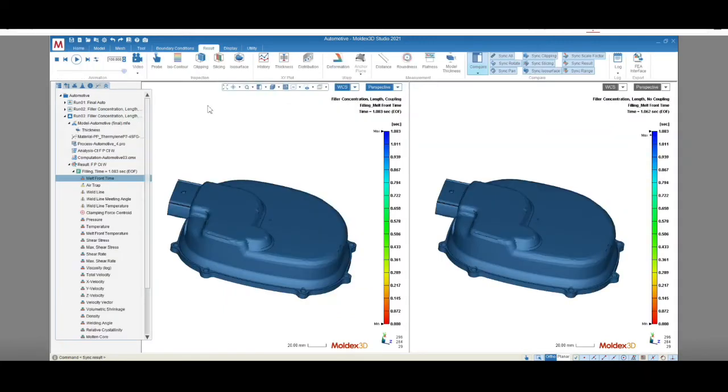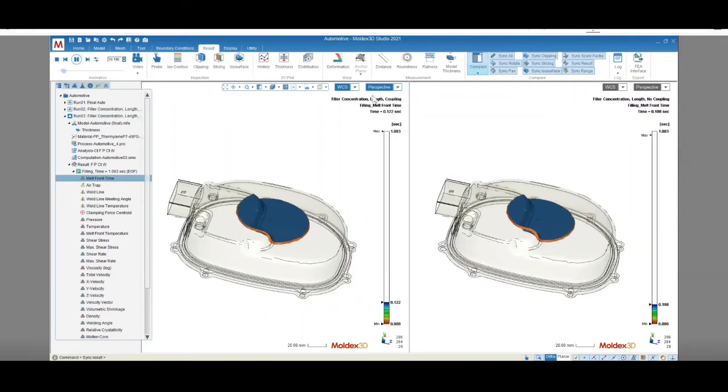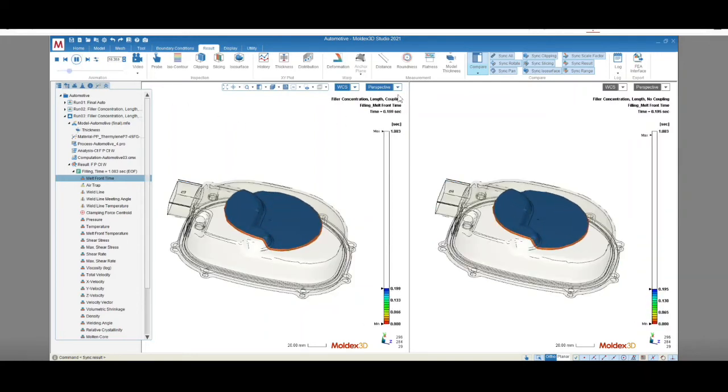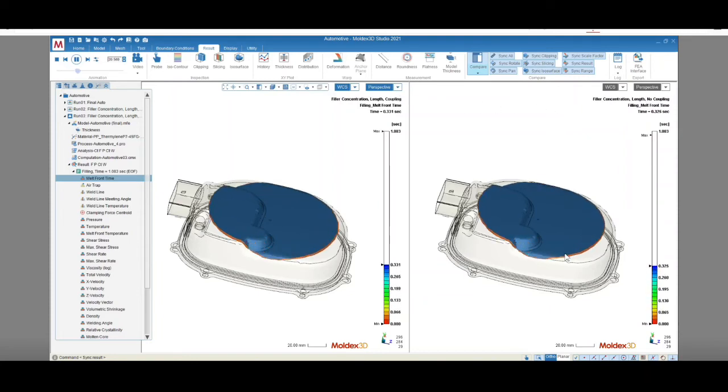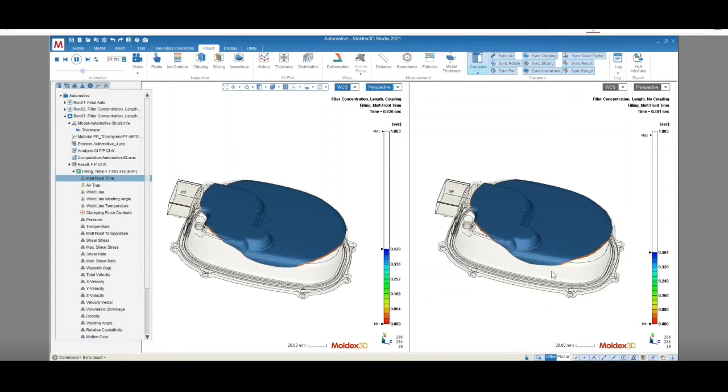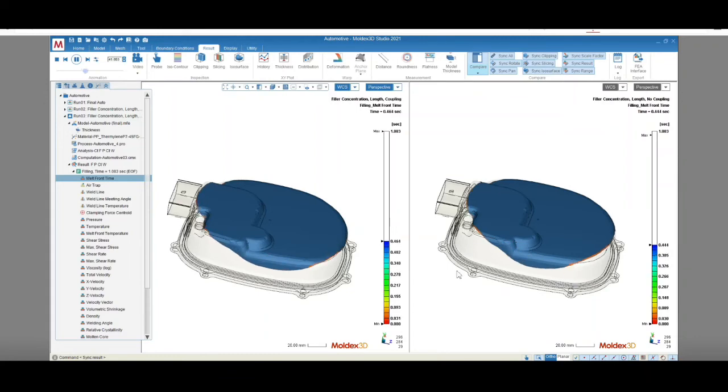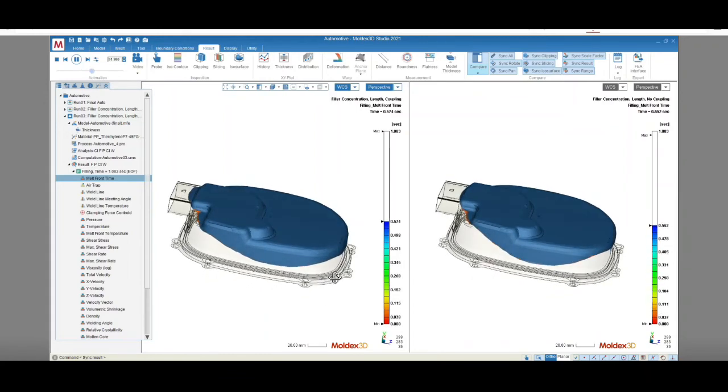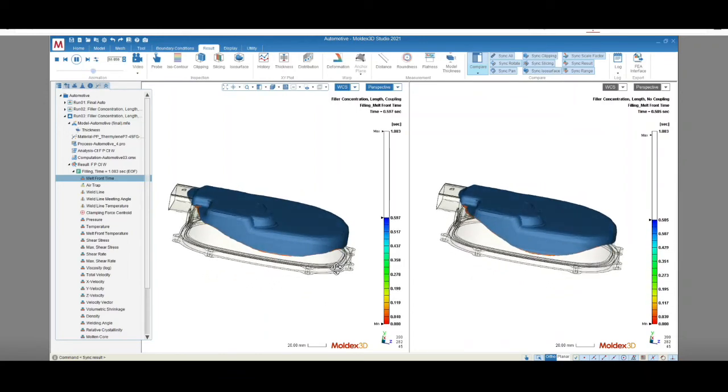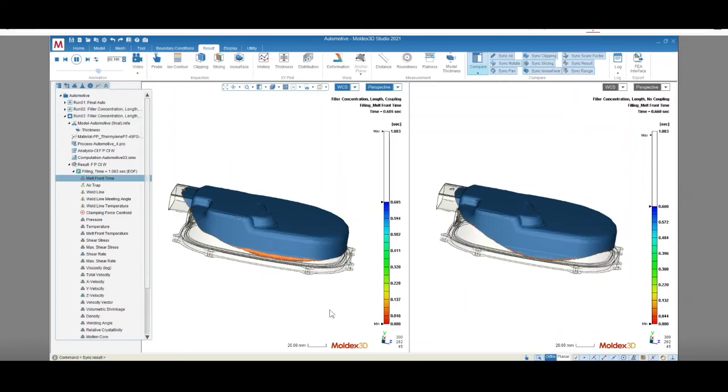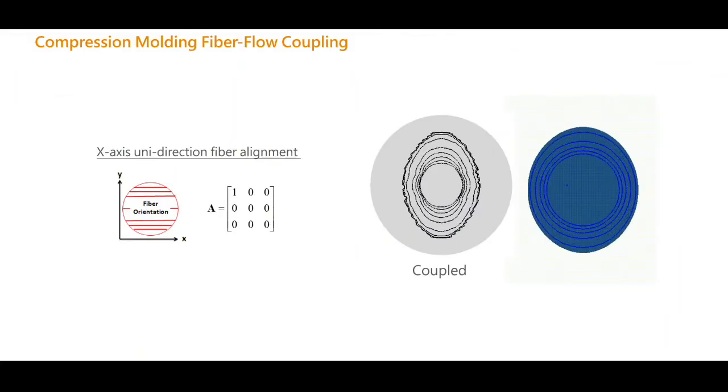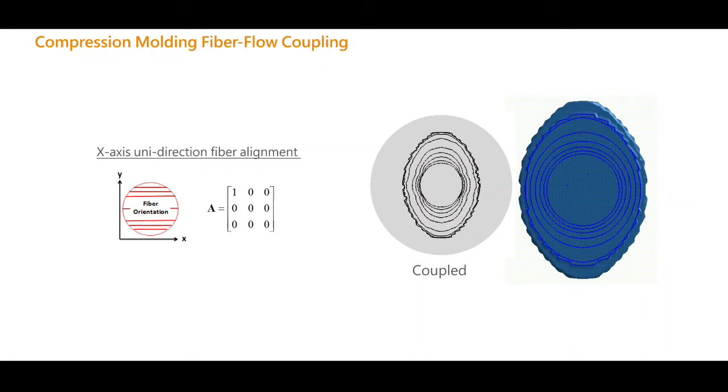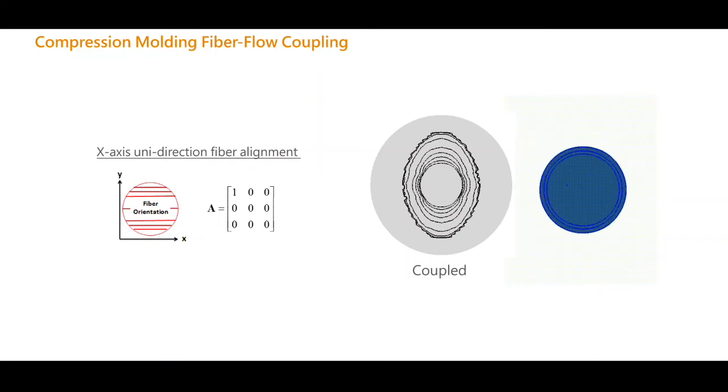Now let's take a look at the results. The model on the left takes fiber flow coupling into consideration, while this effect is ignored in the model on the right. A noticeable difference in the shape of the melt flow front is present around the perimeter of the part. This effect is more pronounced in compression molding, a process in which a charge is placed in a mold rather than passing through a barrel and runner system. Because of this, fibers in compression molded parts can be much longer than fibers in injection molded parts.